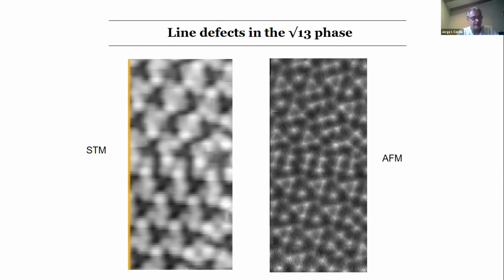We also tried to explore the line defects in some detail. It's easy to look at the AFM image. You can see here a domain with triangles up, a domain with triangles down, and here they are all mostly down. These are the domain boundaries. They look like squares, but actually in the STM images they look different. These are the boundaries, and here there's an equivalence between the two diagonals. I mean, only the diagonal parts of this 4-atom structure are equivalent, while here they look like pairing in this way. I found this distinction between the two images quite nice, and very subtle.